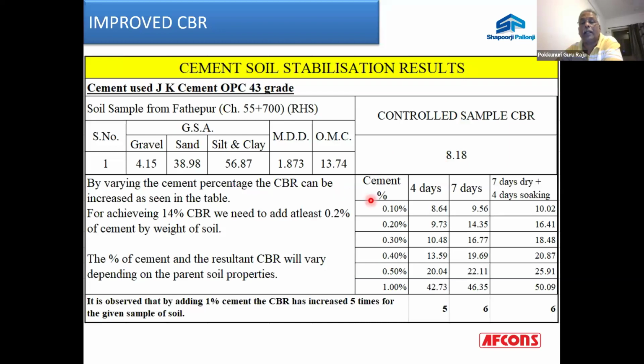But the moment you start adding cement to this particular soil, ranging from 0.1, 0.2, 0.3, 0.4, 0.5, and up to 1%, and you cure it for 4 days, 7 days, or 4 days dry and 4 days soaking, you can see the results. The 8% CBR, when you add only 0.1% of cement, becomes 8.64 on the 4th day, 9.56 on the 7th day, and 10.02 on the 8th day, because it is 4 days dry and 4 days soaking. In the initial 2 cases, it's 4 days soaking or 7 days soaking.